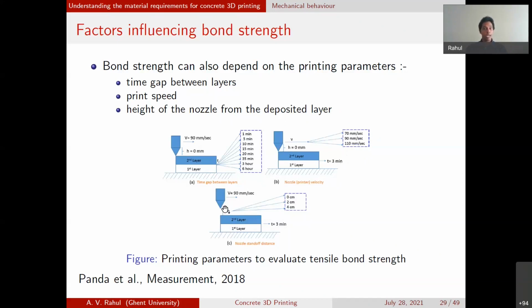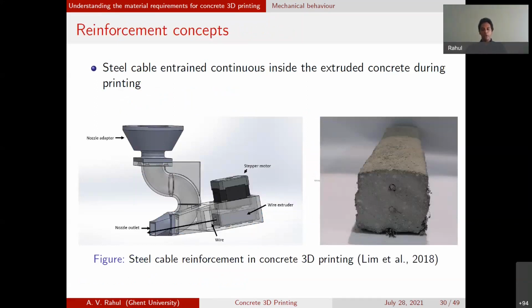And another element is the height from which you're depositing the concrete from the nozzle. So as this height increases, there's less push on the bottom layer, and you see a reduced interlayer performance.